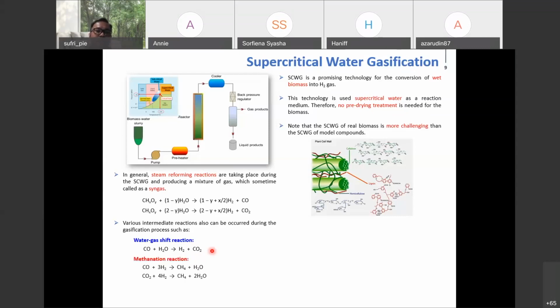Another intermediate reaction is the methanation reaction. The methanation reaction produces more methane. If the carbon monoxide in the reactor reacts with the produced hydrogen, it can produce more methane. Or if the CO2 produced reacts with the hydrogen, it also produces methane. So it means that if this methanation reaction happens progressively, the amount of hydrogen will be reduced and the amount of methane will be increased. So if hydrogen is our expected product, we prefer the water gas shift reaction to progress actively instead of the methanation reaction.